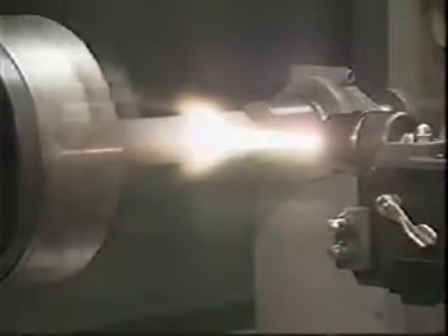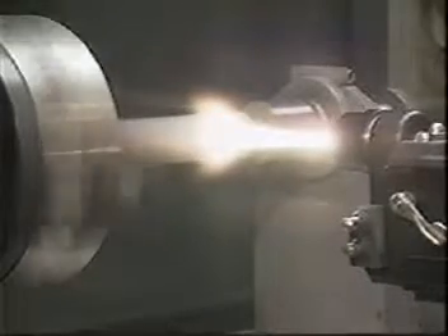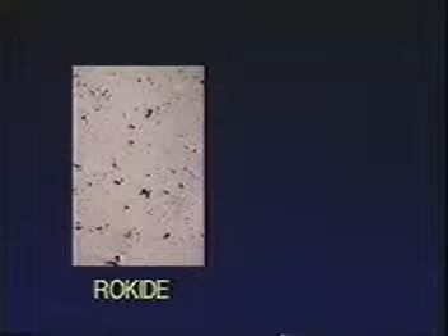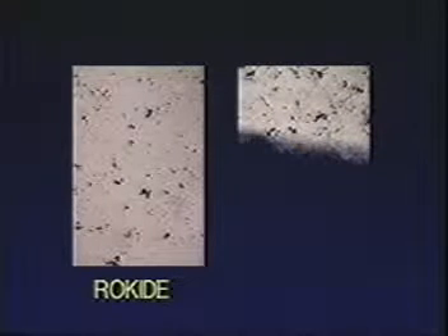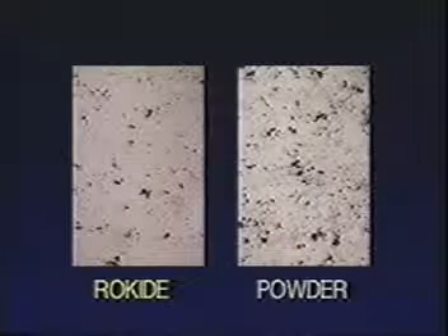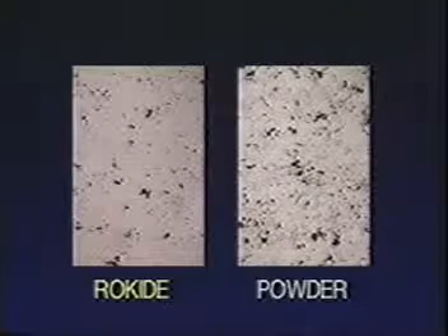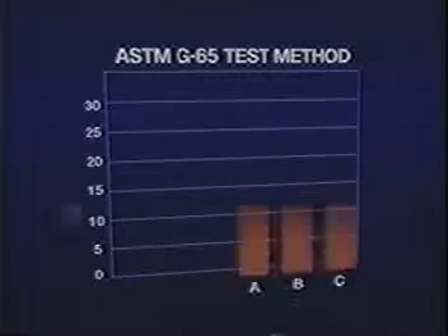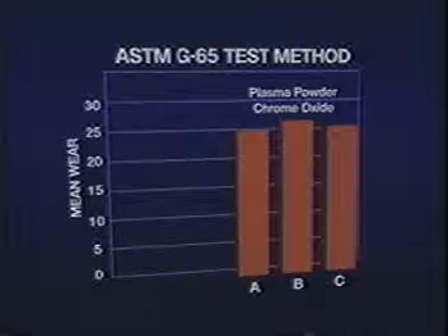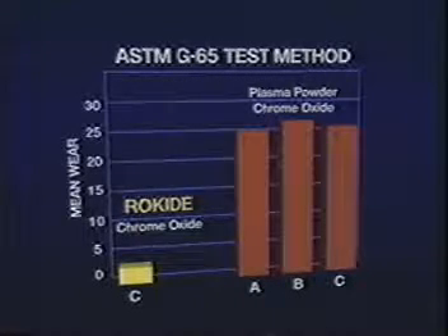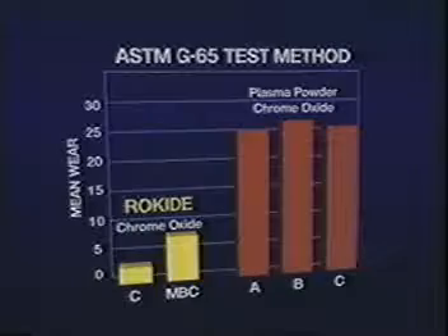And here's a key factor. Rokide particles cannot leave the spray unit until they are fully molten. The result is an even coating with a very tight microstructure, as shown in this photo. With powder systems, not every particle sprayed is in the same molten state. As you can see, the microstructure of the powder system is not as consistent. In abrasion wear tests, here's how much the plasma powder coatings wore away. And here's Rokide C and Rokide MBC.